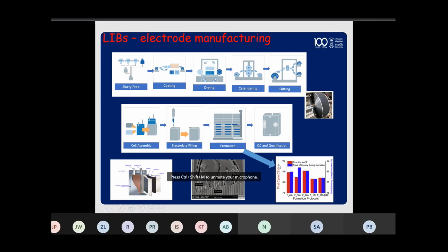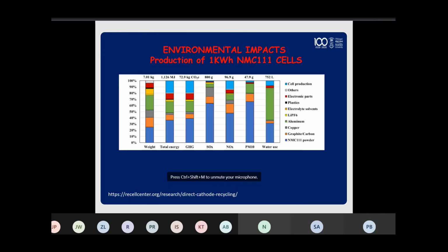So that's the first cycle where you form the SEI, and therefore there are various different protocols to optimize the SEI formation, which in turn determines the performance and the cycle life. So each one of these steps, just in the electrode manufacturing, is fundamental to be monitored in order to diminish the possibility of degradation, to achieve maximum performance, and hopefully to make sure of the safety of the system.